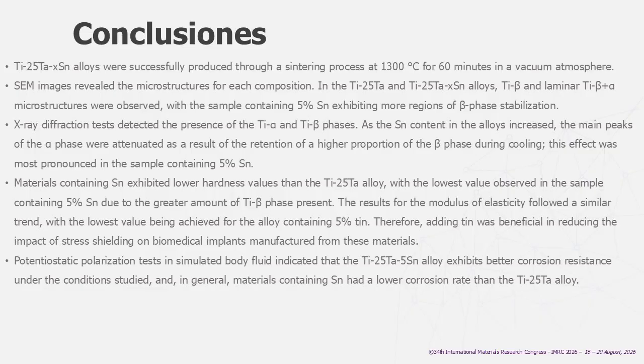And finally, what can we conclude from this project? First, titanium 25 tantalum tin alloys were successfully produced through a sintering process at 1300 degrees for 60 minutes in a vacuum atmosphere. SEM images reveal the microstructures for each composition in the titanium 25 tantalum and titanium 25 tantalum tin alloys. Titanium beta and laminar titanium beta plus alpha microstructures were observed, with the sample containing 5% tin exhibiting more regions of beta phase stabilization.